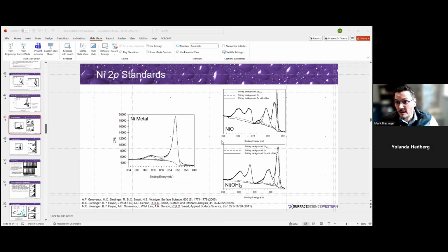You can do calculations relating how big your carbide peak is in your carbon 1s peak to how much carbon you have in your survey spectrum. Then go back and say, okay, if I have that much carbide, how big should that peak be in the nickel 2p spectrum? So you can do those sort of calculations. And then you can go, okay, I know that I should have a peak of this size for carbide in the nickel, then the remainder would be metal. So you can do those sort of calculations based on the information from different peaks.